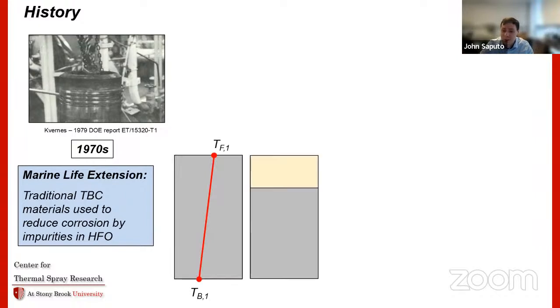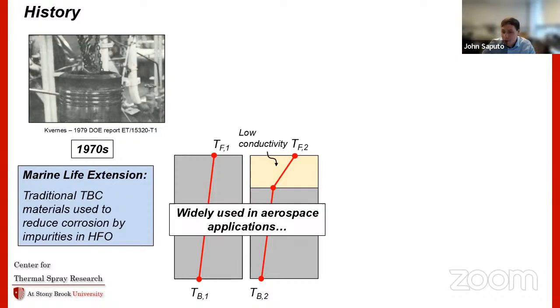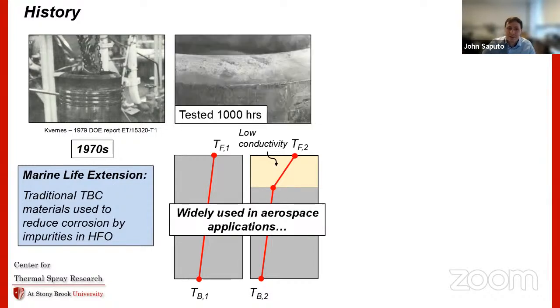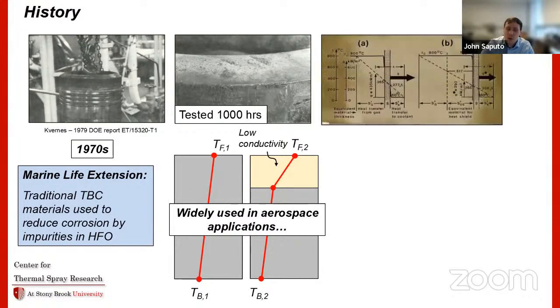So this idea is kind of simple. You have a thermal gradient that runs through one of these systems. You put a low conductivity material on the surface, and the temperature will drop, and you'll have a lower component temperature at the backside. It's widely used in aerospace and tried to transition over to this industry. This is an example of a zirconia TBC that was tested for about 1,000 hours in a marine engine, and you see no real damage. It was only speculated at this time that this could cause benefits to the thermal aspects of the system.